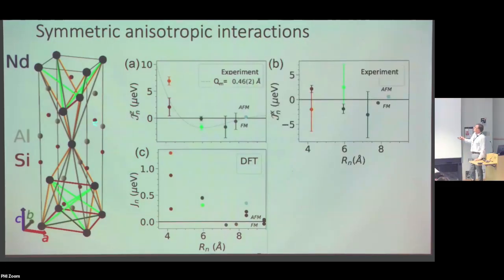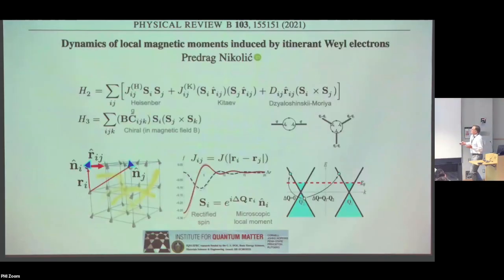But maybe the most important distinction is that there's a transverse interaction as well that we determine from the little rippling of the crystal field excitations, and those are really key to stabilize these canted spin structures that I was talking about. Those are not part of the DFT calculation yet, but of course this is an experimental challenge to say, is it possible to calculate those kinds of things theoretically?